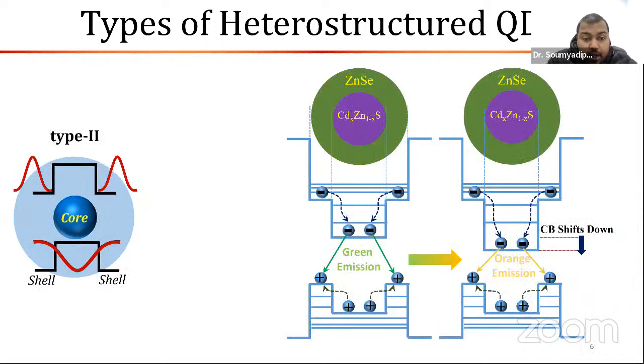Now type 2. In type 1, the band gap of the shell was higher than that of the core. Here, the shell band gap is lesser than that of the core. What happens then is that the exciton generated can relax to the shell, and therefore it emits from the shell structure. So if we have a green emitting quantum dot, due to the type 2 shell structure, it can emit in the orange or red region. So we are basically decreasing the band gap and getting a red emission.